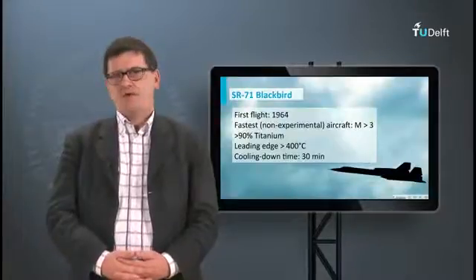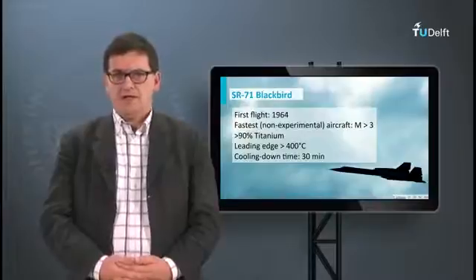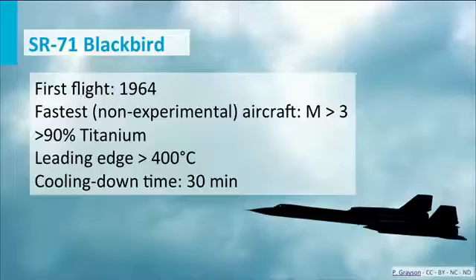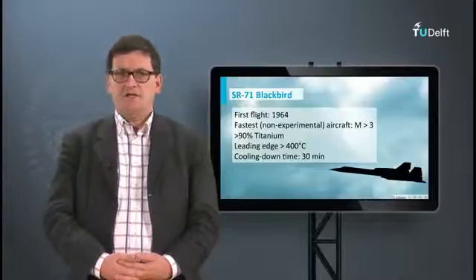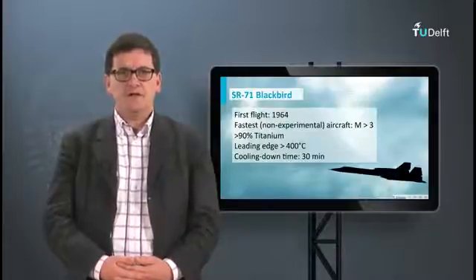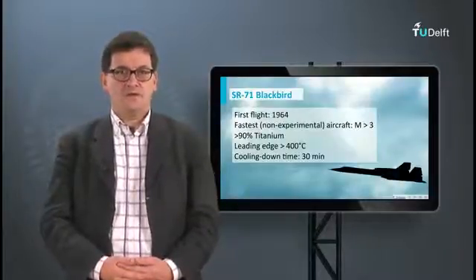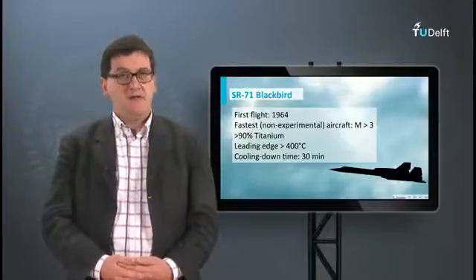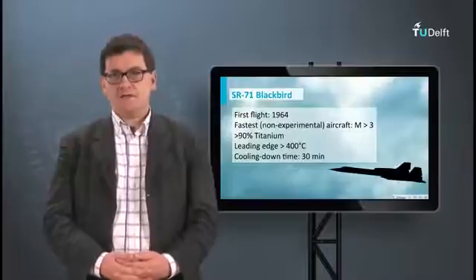Another famous example of a high temperature application of titanium is the SR-71 Blackbird. This aircraft, which is a military reconnaissance aircraft, could fly at high speed and high altitude. The speed was well over Mach 3. Because of the aerodynamic heating of the skin and structure, more than 90% of it was made of titanium alloys. Just as an indication for the temperature, the leading edges are exposed to temperatures of more than 400 degrees Celsius. And after landing, the aircraft needed quite some time to cool down.